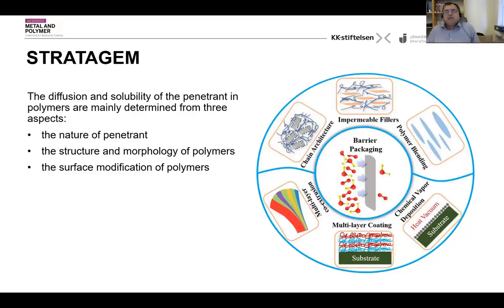Another way of reducing the permeability of the polymers is to use impermeable fillers. For example, nanoparticles could be incorporated into the plastic films, which again provide a tortuous path for the permeating species to follow. And this leads to an increase in the barrier properties of the polymers.